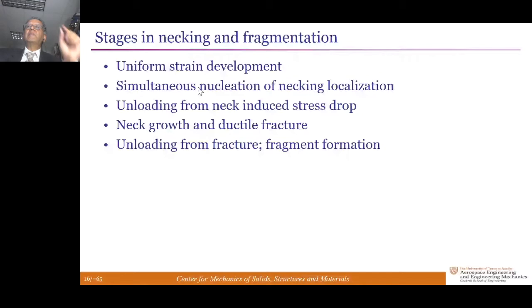The dynamic body force loading, which strains each point independently, allows for this localization to occur at multiple locations. Each localization, as it occurs, unloads a certain domain. And so only some of these necks are able to progress, others are under diminishing loading. Some of those things go on all the way to fracture, but the other parts remain unloaded and they stay deformed and they provide more information about what happened during the fracture event. You could collect all these fragments and do statistics of the fragment distribution and so on. I'll get to that in the next few minutes.